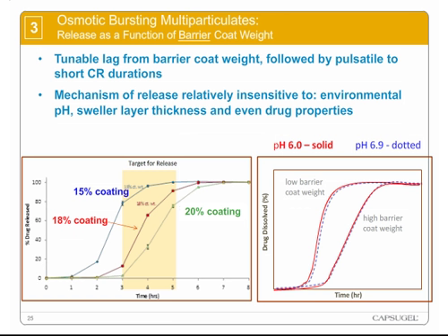The mechanism of release is relatively insensitive also to a wide variety of parameters such as environmental pH. Showing the graph on the right side, what's shown here is at 2 different coat weights, low or high barrier coat weight, and at 2 different pHs, pH 6.0 versus 6.9, these particles can achieve the same release rate independent of pH. This is important back to my thought on the patient-to-patient variability, that if a patient population due to a disease state or their diet or their age have a different pH profile throughout their small or large intestine, these particles will still release at a very prescribed time. And that's, again, important to efficacy in this product and in other projects that we've had.